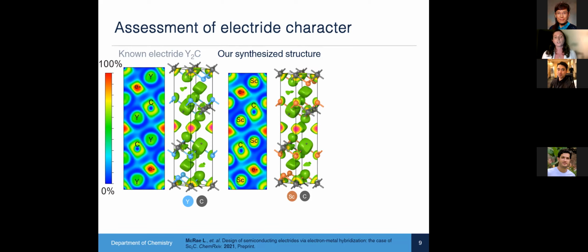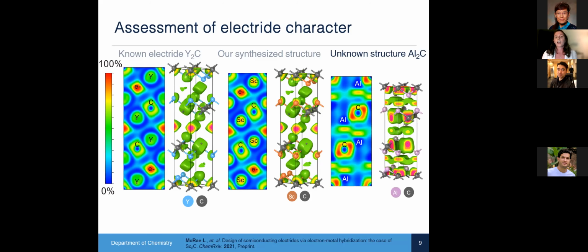So we decided to incorporate an even more electronegative atom, aluminum, into the same structure and see if we would still get the electride character. And so you can see now in aluminum carbide, we do have some amount of electron localization between the aluminum atoms that I'm pointing out here, but it's not localized in sites in the same way that it is in the scandium carbide case. And so our conclusion from this is that there is a spectrum of electride character based on the electronegativity of the cation. And because aluminum is more electronegative than scandium, we see still some electron localization, but not as much electride character as we're seeing in the scandium and yttrium carbides.